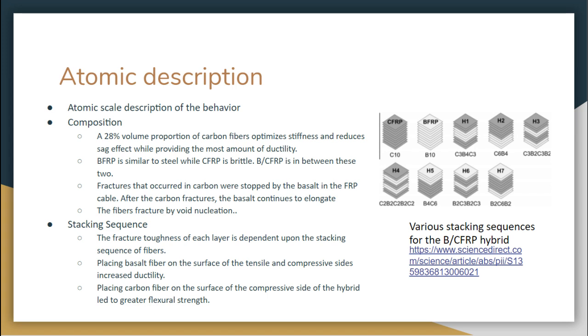The range of ultimate tensile strength in these hybrids is close to the strength of CFRP, while in most of these hybrids we can see that rather than brittle fracture, there is some plastic deformation before fracture. One combination that we thought would work for bridge cables includes the 28% of carbon. This combination is good because it leads to high ductility and a high tensile strength, as well as no sag effect when load is being applied on the cable.